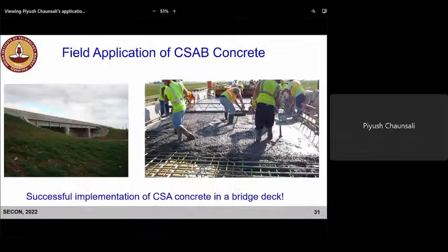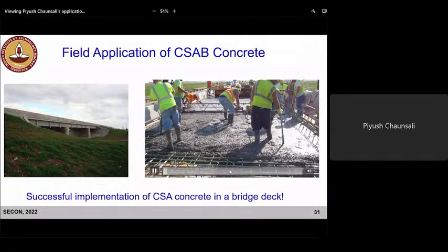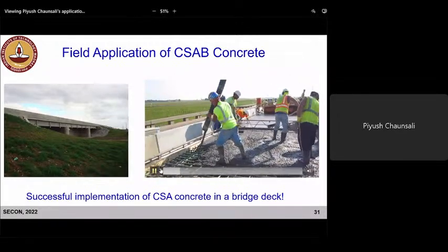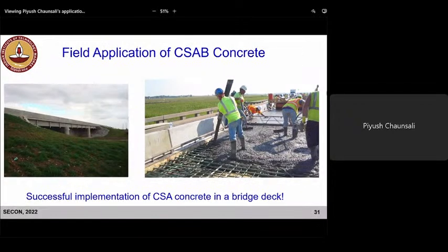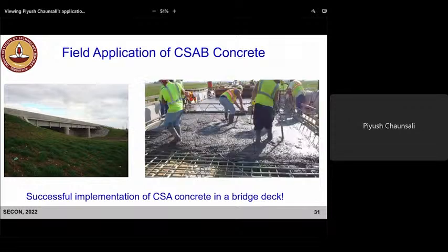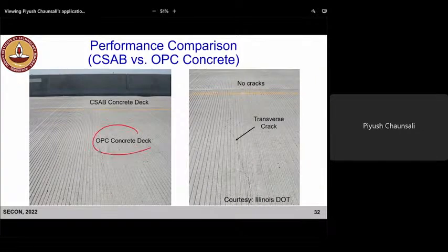So I will show you a field application. I was involved in this. This is a bridge deck in the state of Illinois in USA, where we developed this CSAB concrete, and this was a test study where we wanted to see the difference between CSAB cement concrete and Portland cement concrete as far as shrinkage compensation is concerned. So we cast two slabs, one with the CSAB concrete. You can see it was quite workable, had a good finish, and then we also cast the OPC, Portland cement concrete deck, next to this CSAB concrete deck.